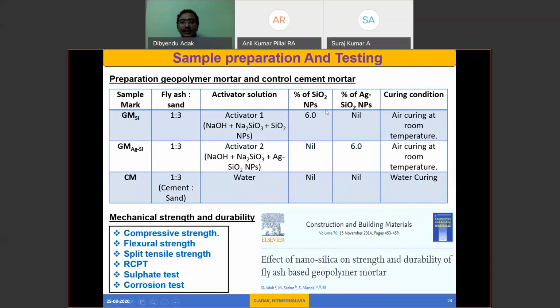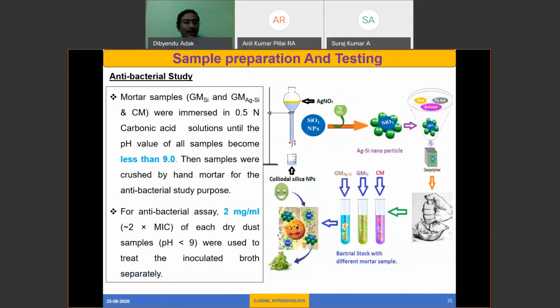Now here we can see that 6% silver nanoparticle content and 6% silica nanoparticle content have been used. This is based on research showing that 6% nanosilica gives better strength of geopolymer concrete cured at ambient temperature. So based on these three mixes, first I will show you the results on compressive strength, flexural strength, RCPT value, and then the antibacterial property. So this is how we have studied the antibacterial property.